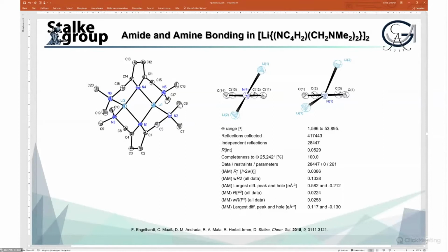If we refine the molecule with the independent atom model approach, there are reasonably good values. The WR2 is pretty high because we have so much data. It turns better if we multipole refine the molecule, then the R value gets even better. And which is most important, the residual density map got even more flat and featureless.